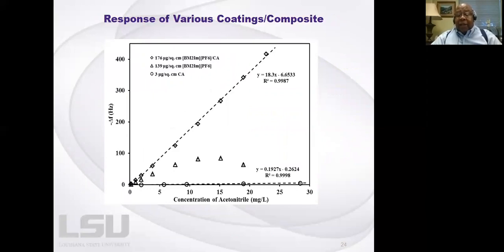And the response was very interesting, because for our particular material at the top, where you have 176 micrograms of material, that was the linear relationship. And down at the bottom, where you look at just the ionic liquid and the other material, he made a mixture of cellulose acetate. The top one is a composite of cellulose acetate and the ionic liquid. The other one that has a curve is simply the ionic liquid, and the bottom one is the cellulose acetate.